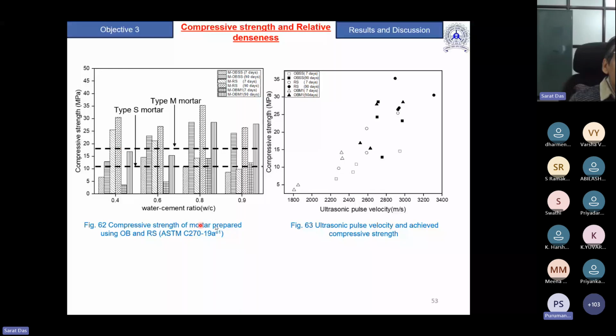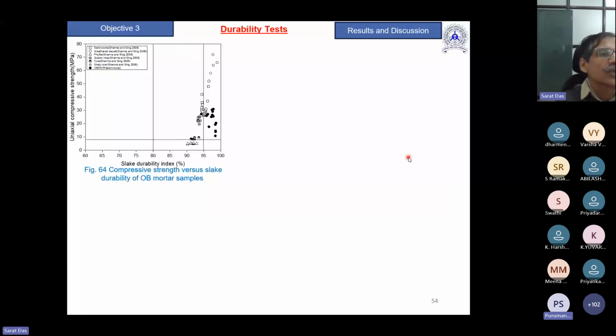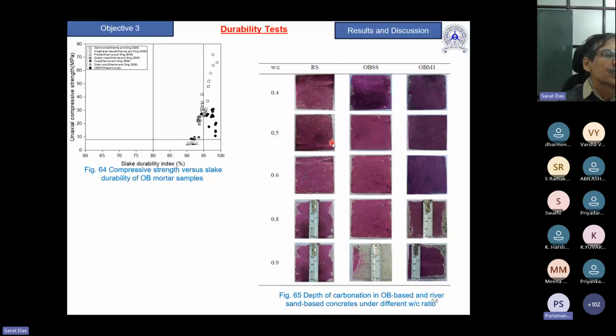Another aspect we want to study is whether this sand creates any void in between, which you can check using ultrasonic pulse velocity. And there I found that the strength increases, the value is also increasing, and 3000 is a good value. Next, you need to also do durability tests. In the durability test, you can go with a slake durability index test. We have done it for different materials, including OB. OB has got a very high value. And then also you can go with depth of carbonation. A carbonation chamber test you can do, because you are going for durability.